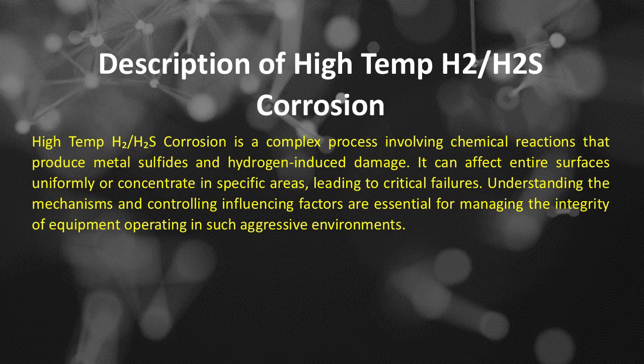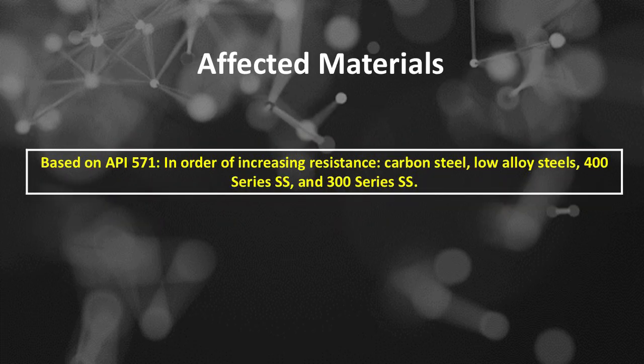It can affect entire surfaces uniformly or concentrate in specific areas, leading to critical failures. Understanding the mechanisms and controlling influencing factors are essential for managing the integrity of equipment operating in such aggressive environments. High-temperature hydrogen (H2) and hydrogen sulfide (H₂S) corrosion affected materials based on API 571, in order of increasing resistance: carbon steel, low-alloy steels, 400 series SS, and 300 series SS.